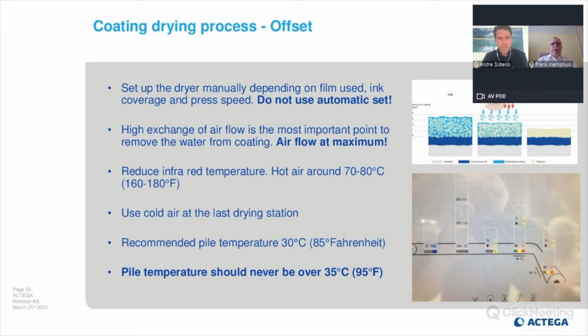What about the drying of the coating in offset processing in the coating unit? So that is what I explained. You have to evaporate the water. It has to leave the coating film. And if you have the coating unit in an offset processing, you have IR dryer and hot air. And we recommend don't use the automatic setting for IML. It could give you a wrong setting. So it's better to set it manually, to see, okay, what you need is the air flow on maximum.